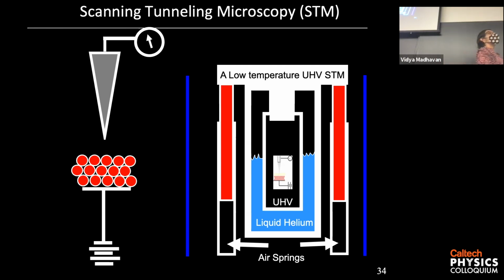And then you apply a small potential difference, and electrons can tunnel across the vacuum barrier from the tip, we call this the tip, to the sample or from the sample to the tip. And the measurement that we make in STM, there's only one measurement that we make, and that is the magnitude of the tunnel current. So we measure the tunnel current as the tip is swept across the sample to obtain topography. We can measure the tunnel current as a function of bias voltage to measure density of states and so on. So it's a very simple technique.